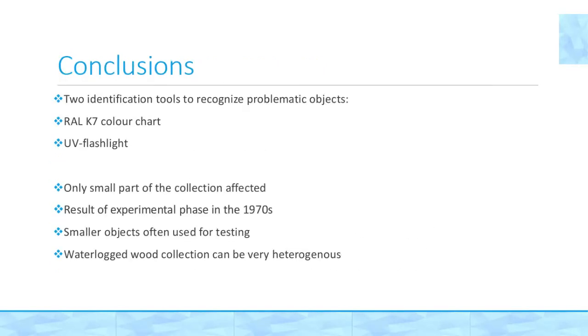This brings me to my conclusions. I would say that I've managed to successfully identify problematic objects based on, firstly, color, and then, secondly, confirming my suspicions with a UV flashlight. Using the flashlight is essential, since the collection also houses other dark-looking objects that do not stick, leach, or have this distinct fluorescence. Only the objects that showed this distinct fluorescence and the dark color were the affected objects. I also managed to conclude that only a small part of the collection was affected, and that this is most likely due to an experiment that was conducted in the early 1970s.